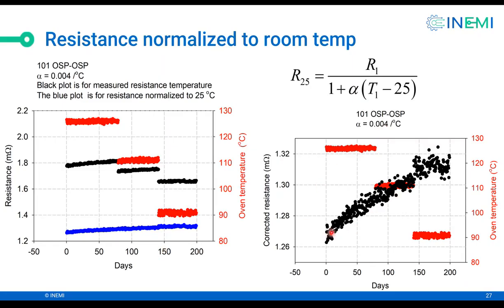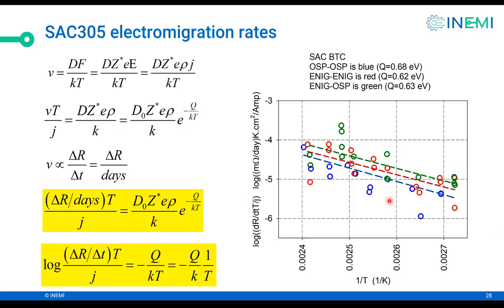So now we have three temperatures, 1, 2, 3. We take three slopes and we can use them to plot the Arrhenius plots. Again, as I showed earlier, we plot the log of rate of change of resistance times temperature divided by current density, which is equal to minus Q over k times 1 over T. So we're plotting the log of that function versus 1 over T, and we get the Arrhenius plots. Notice the blue is OSP, the red is ENIG, and green is ENIG-OSP. We get very similar results. So finishes don't play a role in electromigration. It doesn't matter what the finish is.